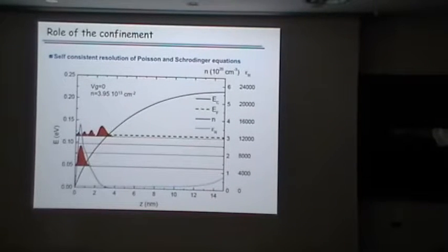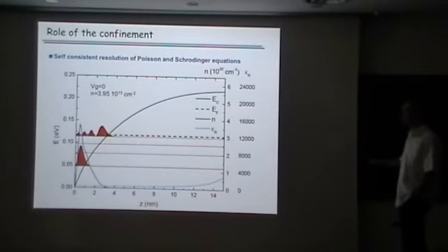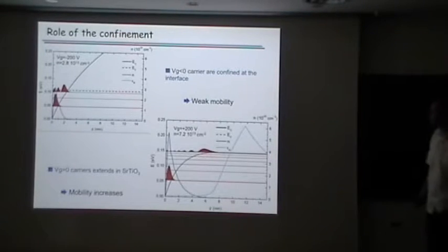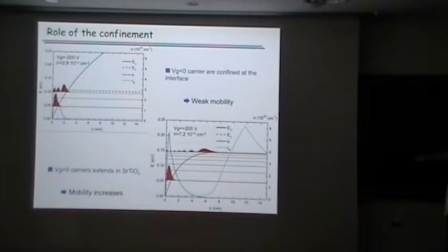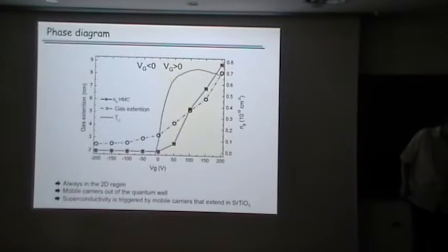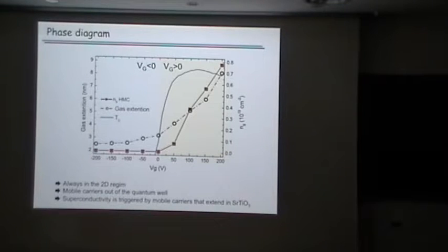And you have a strong peak of the number of carriers. We put here the number of carriers converted to 3D, with a maximum and a small tail. It's a log scale here. And then in this calculation, we have a few sub-bands filled up to the Fermi level here. And then when we remove electrons, we have a few electrons and only a few sub-bands very deep in the well, which are populated. And if we put a positive voltage of 200 volts here, then of course we extend the gas, and you see we put in more and more electrons, but what is very important here is that you extend the gas more and more. And in fact, what's going on is that when you increase the gate voltage, not only do you change the number of carriers, but you change the extension of the gas quite a lot.